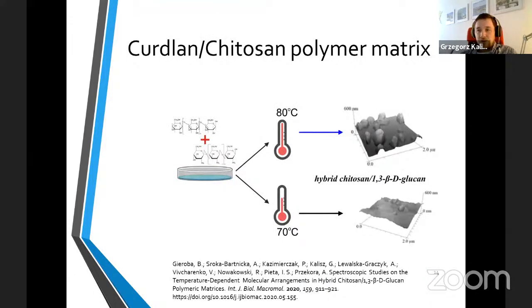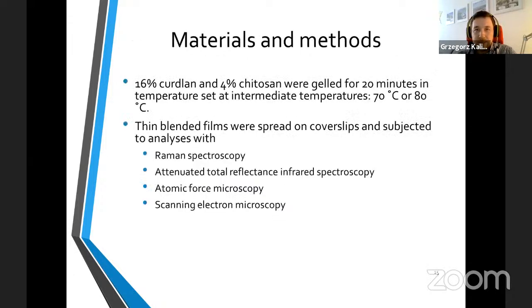Later, we decided to perform similar research on Curdlan chitosan hybrid matrix. It was also published, but we decided to choose different temperatures. They were more intermediate, 70 degrees and 80 degrees. Also, the procedure was similar. Gelling of Curdlan happened for 20 minutes in different temperatures.